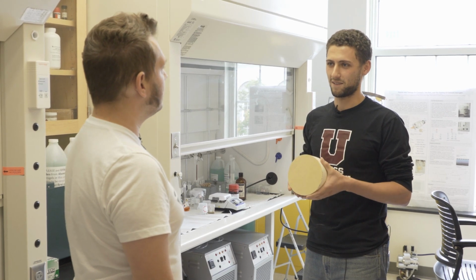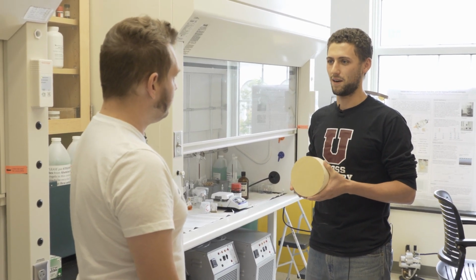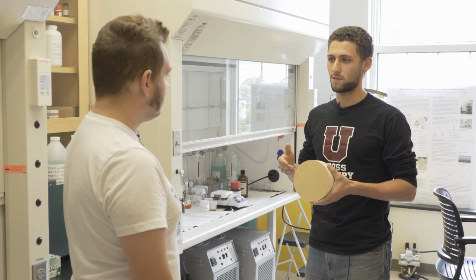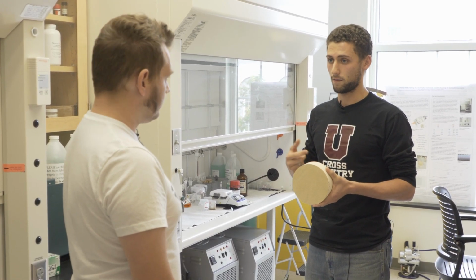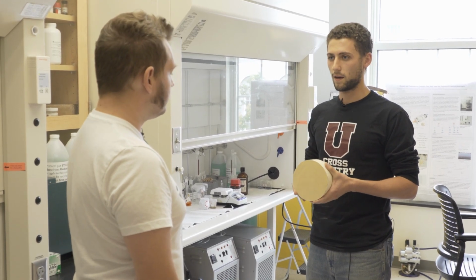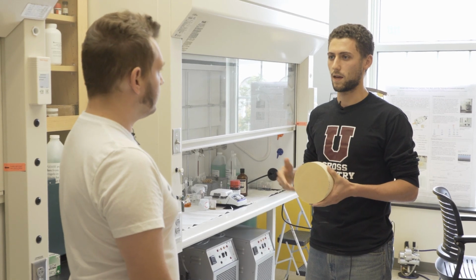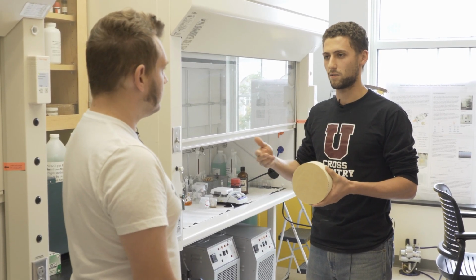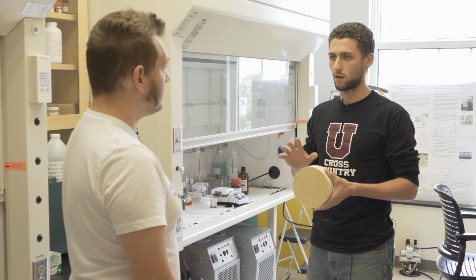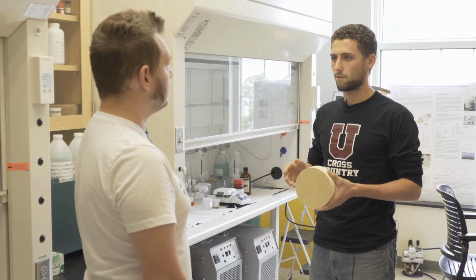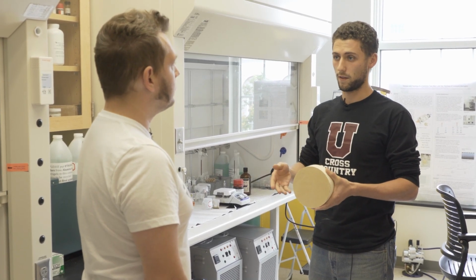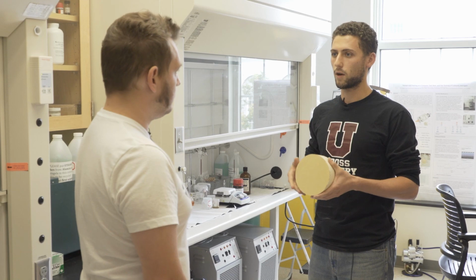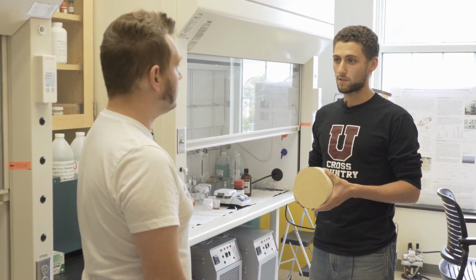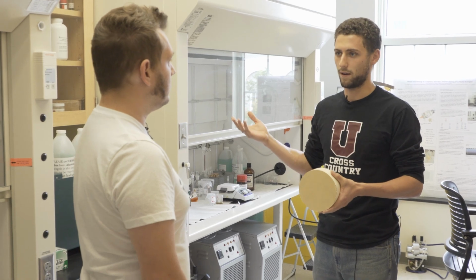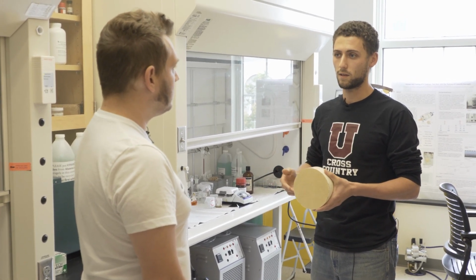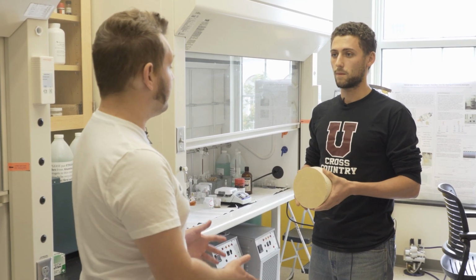Initially, nothing really stuck. And visibly, I would take out my samples, even after various methods were tried, from the hot press, and pieces of aerogel were there, and they would fall off or fall out of the channels. And then I did some SEM, so scanning electron microscopy images, some energy dispersive X-ray spectra as well to see what was stuck that we couldn't visibly see, and we saw an even but very faint distribution of our aerogel in there. So we realized there was something, not a lot. Okay, we'll catalytically test it anyway. And despite having, within significant figures, 0 grams, essentially, of our aerogel on the material, we were actually getting some catalytic activity. So a little bit of aerogel goes a long way.